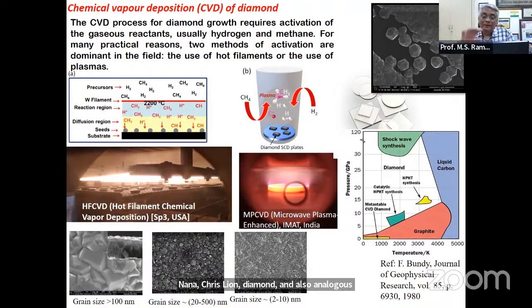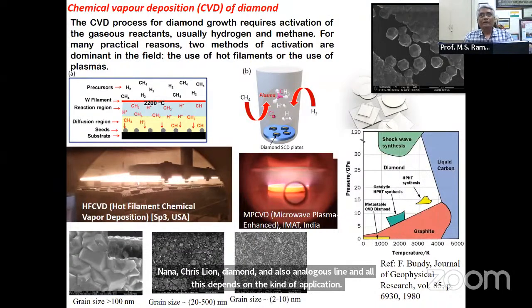But then if you want electronic or optical grade diamond, you need to go for microwave plasma CVD in order to eliminate the possibility of any defects. But diamond also can be grown using high pressure, high temperature technique. This is a big challenge. We are going to take up this challenge also to build machines for making high pressure, high temperature synthesis.